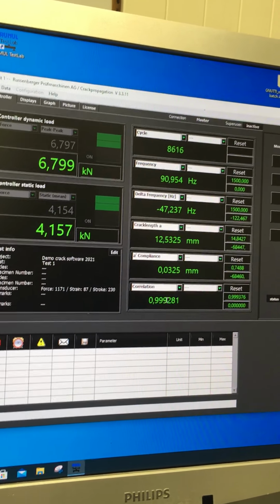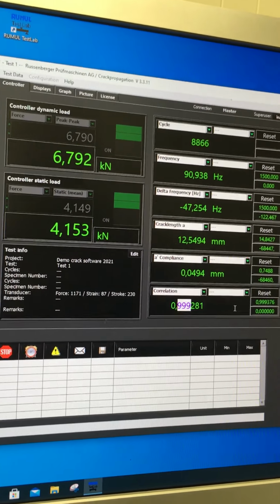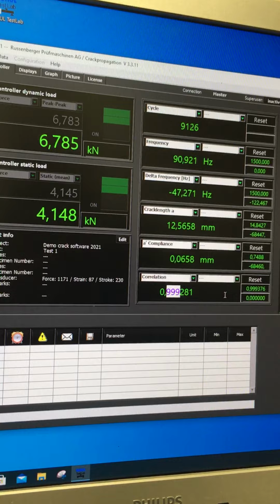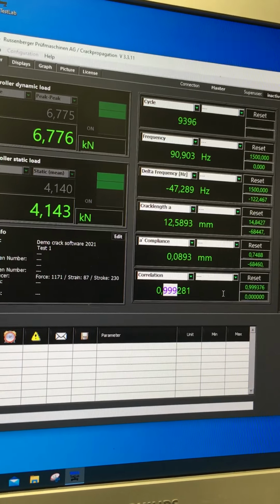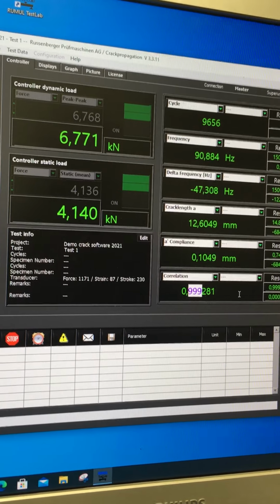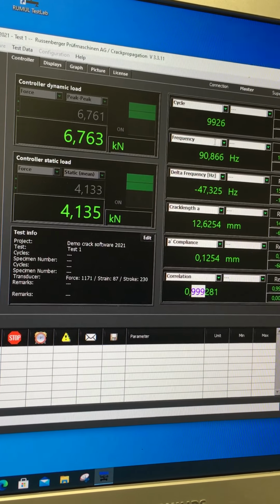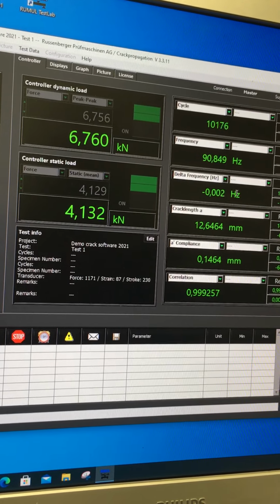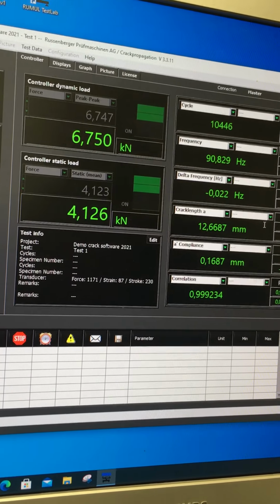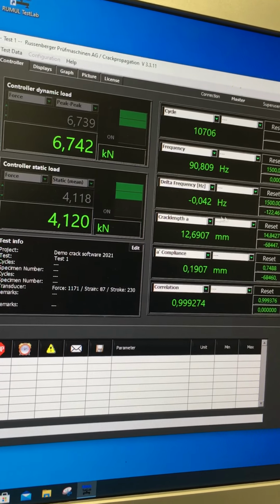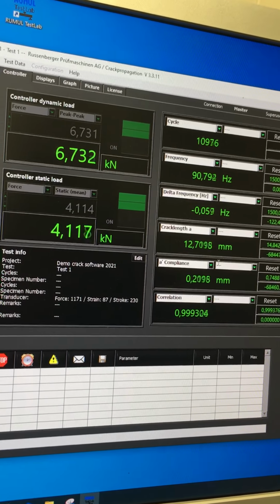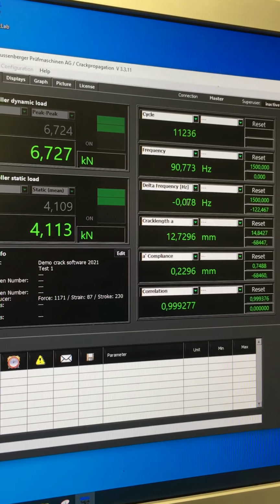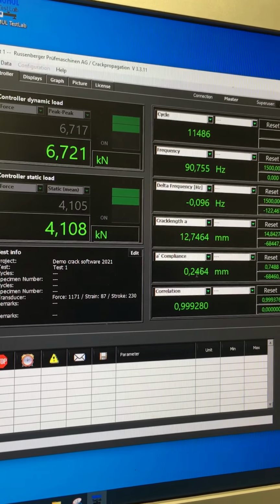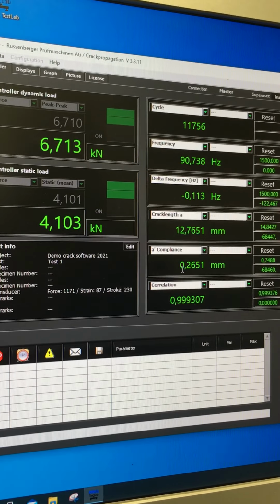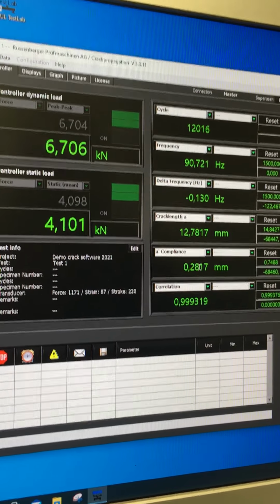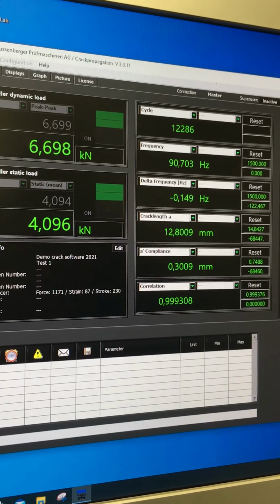A good indication is also the correlation. This is the correlation of the slope. The nearer to one, the better. So this looks quite good. The most reliable system, however, to see if a crack is growing, is the change of the testing frequency. As we see here, it is already running. The frequency is going down slowly, and also the crack length measurement is increasing, so everything is consistent.